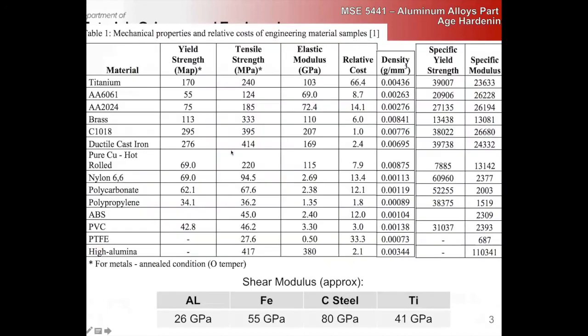So if we just look at some properties here and compare, this is 1018 carbon steel and 2024 and 6061. So 2024, what's this alloy? This is aluminum copper, a very famous alloy developed during World War II for aircraft skin, right? Very high strength at the time. Unfortunately, really, really bad in corrosion. The way they get around that is to plate a layer of pure aluminum on top of the aluminum copper alloy, so that you can get some corrosion protection then, right?